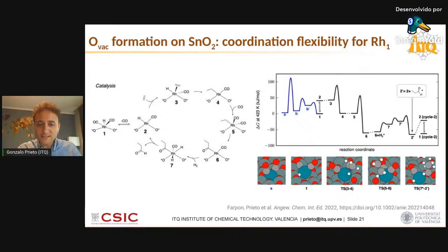So I think this is illustrating in a way how oxygen lability and the gaining of coordination flexibility for oxide-supported single-atom centers can approximate their mechanistic routes to those of the molecular counterparts operating in solution, and therefore be perhaps a potential way to bring performances for solid catalysts close to those of the optimized molecular catalysts in homogeneous catalysis.